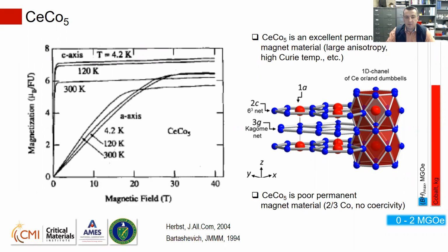Cerium cobalt 5 is a calcium copper 5 type compound, and from the literature we know that it's a very good candidate for permanent magnet development, but for some reason cerium cobalt 5 is not a permanent magnet. It is an excellent permanent magnet material because it has large anisotropy, it has high Curie temperature, etc. But on the other hand, it is a poor permanent magnet material, especially from the perspective of cobalt content. On the right side of this slide, you see the indicator, where you see how much cobalt you have and how many megagauss it produces. So basically, it's cobalt which produces nothing.